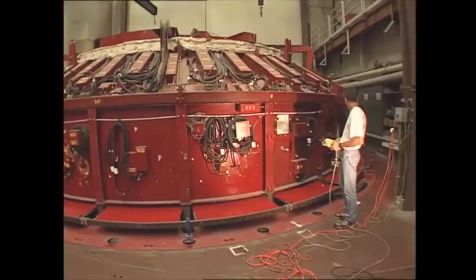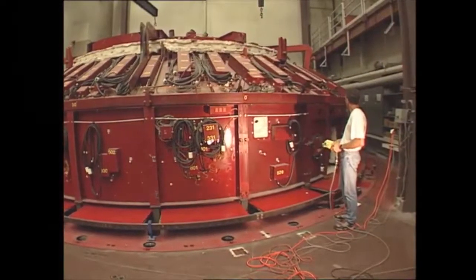The oven starts to spin, reaching a peak speed of about 5 revolutions per minute. Within it, a carefully controlled temperature cycle begins, which will reach a peak temperature of 1160 degrees Celsius, hot enough to melt the glass. As the glass melts, it liquefies and falls between the shapes of the hexagons, filling the space between them and leaving a 1-inch faceplate that's in the perfect parabolic shape as the oven spins. Then the temperature is slowly reduced.